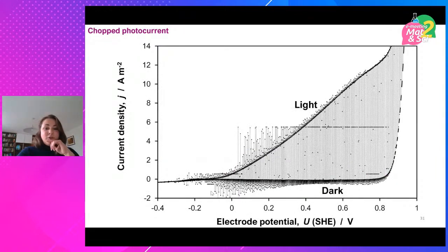And finally, the chopped photocurrent squared technique. This one we did manually, so all of the chopping was done with a credit card. So we had a steady light source. We did this with white light. We did this with monochromatic light, and we basically scanned the potential really, really slowly, 1 millivolt per second, from negative values to positive values. And we manually chopped the light on and off about once every 3 seconds.